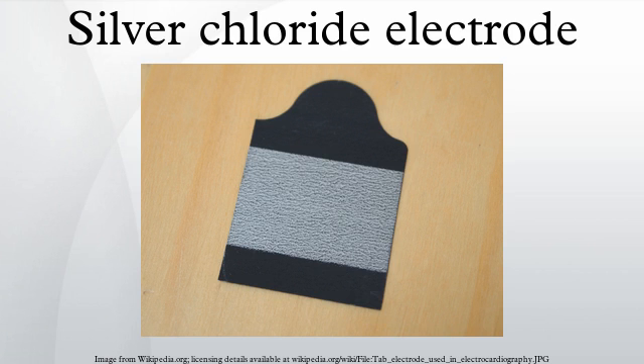The electrode has many features making it suitable for use in the field: simple construction, inexpensive to manufacture, stable potential, and non-toxic components. They are usually manufactured with saturated potassium chloride electrolyte, but can be used with lower concentrations such as one mole per kilogram potassium chloride. Changing the electrolyte concentration changes the electrode potential. Silver chloride is slightly soluble in strong potassium chloride solutions, so it is sometimes recommended that the potassium chloride be saturated with silver chloride to avoid stripping the silver chloride off the silver wire.